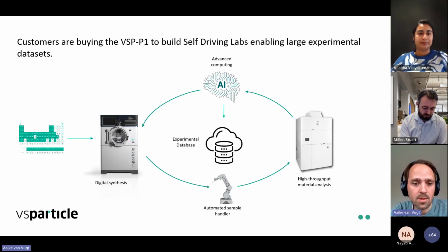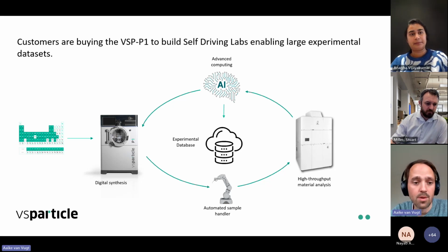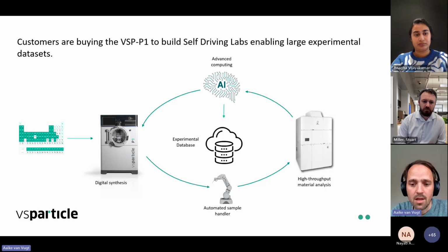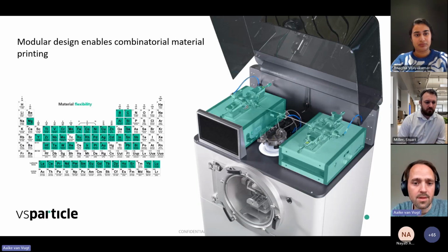And there I would like to spend a little bit more time explaining why the P1 is such a valuable asset if you want to build a self-driving lab for inorganic materials or for inorganic nanoporous materials for energy applications. So first of all, the standard P1 can be equipped with 2 nanoparticle sources, and it has a huge flexibility in the material space. So our core technology is making use of electrical sparks between those solid rods to evaporate the material. And at the spark, we created temperature going up to 20,000 degrees Celsius.